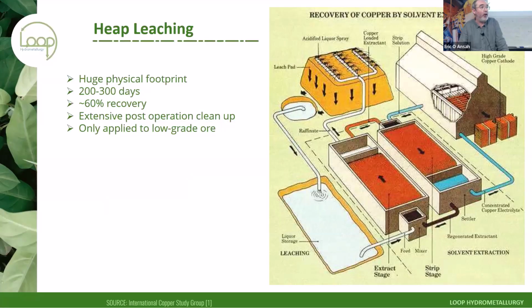Now, heap leaching is a perfectly sound option for incredibly low value, low concentration ores. But you know, you're going to be waiting 200 to 300 days to get 60, maximum 65% recovery. So it's not at all efficient. And of course, by the way, increasingly these heap leaching operations are facing a really interesting challenge. They work off sulfate chemistry, but if the site is saline, you go from having 4 or 5 sulfate species to deal with, an iron sulfate, a copper sulfate, maybe a zinc sulfate or whatever. The second you introduce chloride, now you're going to be dealing with 20 plus chloride species because the chloride chemistry will dominate. You'll have an unholy mess of different redox chemistries, of different pH, precipitation points. Your heap is going to become a big old mess.